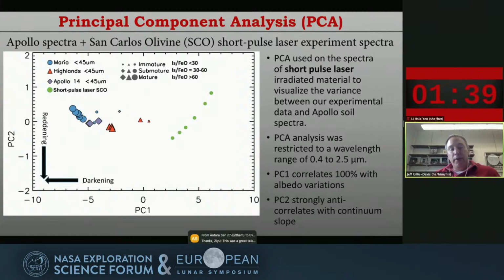Now I've popped up these green circles, which are results from our short pulse only laser. One takeaway is that the immature material from the moon is still more mature than what we did with the short pulse laser in this scenario. But you can see the trend is roughly what we see, but definitely steeper. We get a lot more red with our short pulse.